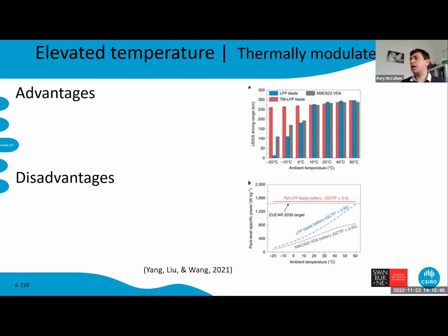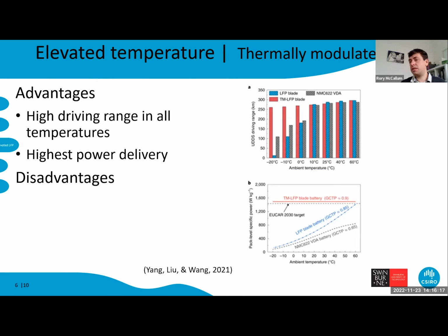But what happens if we just heat it whilst we're using it in an EV situation, where most of the time they're just stationary? Well, we can see if we take an LFP cell and do this, we get really high driving ranges in all conditions. So this is the red line you can see versus the blue line for just the standard LFP cell. And we see high power delivery under all conditions. It only uses about 2 to 4% of the battery pack to heat it up, and we can charge them in 6 minutes. And this is just using standard off-the-shelf LFP cells.